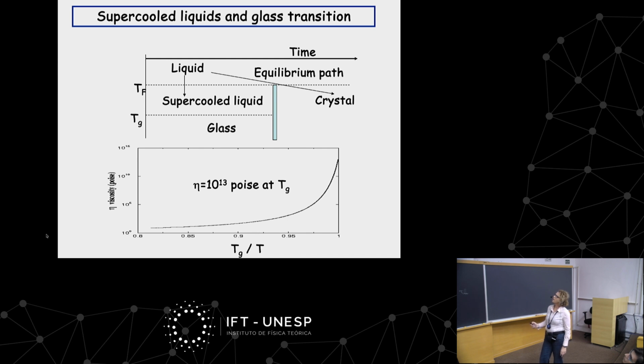So how can I distinguish between this path and this path? Simply by taking away kinetic energy very fast from the liquid, so as to avoid the bypass crystallization. So the liquid gets lower and lower and eventually freezes in a disordered form, which is a glass, at a temperature which is the glass transition temperature.